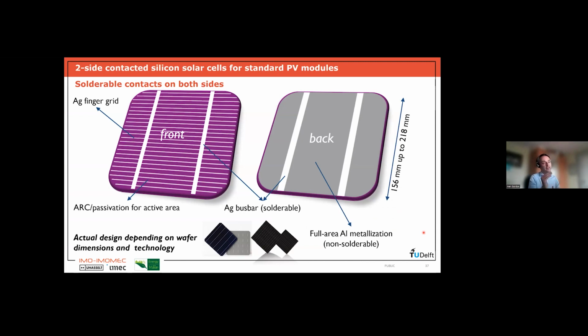That means you have a metal contact at the front and at the rear, and how these in standard PV modules are interconnected. So just to remind you, this is how the front and the rear of the solar cell look like. At the front, we have silver. We have these fingers, which are connected by bus bars, which are solderable. And at the rear, we typically have the whole rear of the wafer covered by aluminium, but typically you also have some silver bus bars there for solderability. Of course, in reality, especially now that we have these very large wafers, the actual design of these grids can vary from cell to cell. And here I show you only 2 bus bars. In reality, most cells that are produced now have many more bus bars, like 5 or even 9 or 12. It depends on the technology, but the principle is of course always the same.